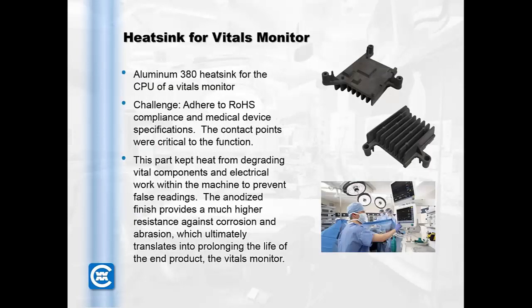The next one here is a heatsink. This is for a vitals monitor that you would see in an OR or doctor's office. This is an aluminum part. The challenge here was that the part needed to be fairly lightweight and very good for thermal conductivity in order to get heat away from the electronics. And so in this case, it was a good choice for an aluminum part. This part gets anodized. You can see it's sort of a brown, lightly black. I don't know how you want to call it, but it's anodized, which helps with corrosion protection and some wear resistance and prolongs the life of the product.